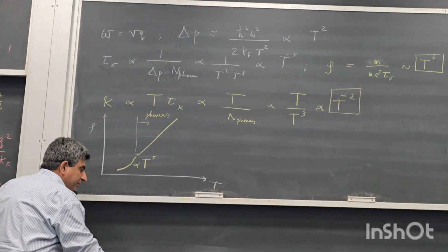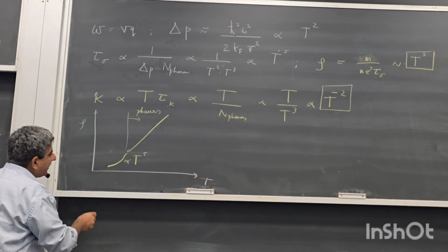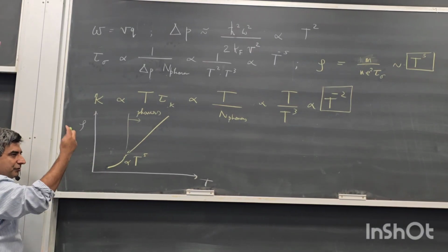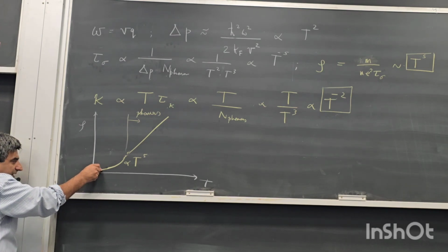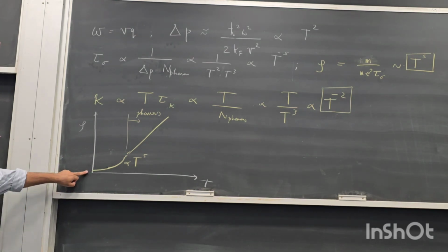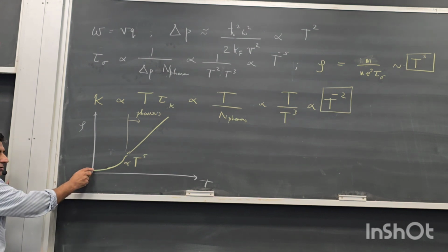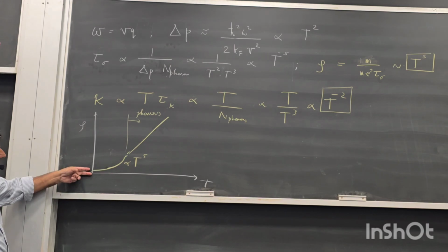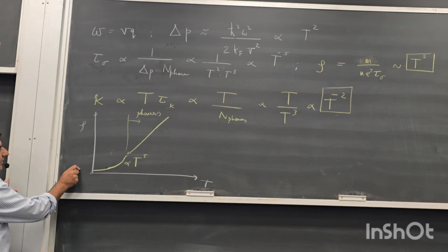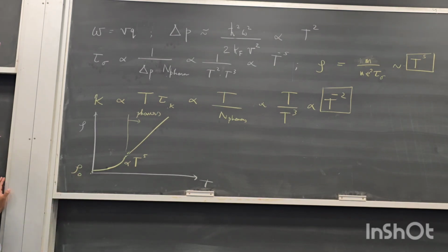And what happens in practice is that at really low temperatures, say close to a few kelvins, this electrical resistivity just becomes constant at some value, this intrinsic non-zero value to which this electrical resistivity settles down. Let's call it rho naught.